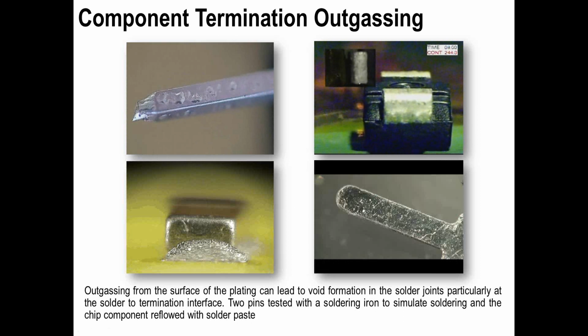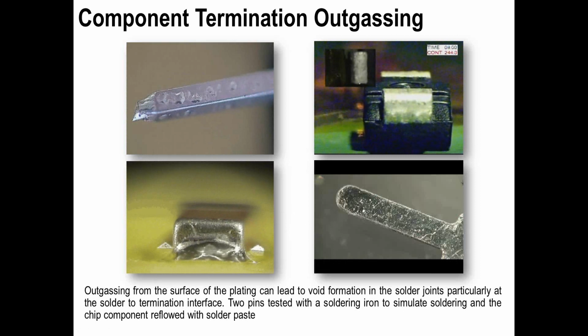And the reason I'm showing you this is just to highlight that it's not always the paste, it's not always the profile. On these 3 examples from my library, I can demonstrate to you that the component was the root cause of the voiding issue. If we look at the bottom left now, and this is just a chip capacitor, if you look at the surface of the plating on this capacitor, it's going through the reflow cycle. We're not looking at where the solder joint is forming, but you can see quite nicely the gassing from the surface of the plating. So again, perhaps one particular supplier was causing a problem more than the other.